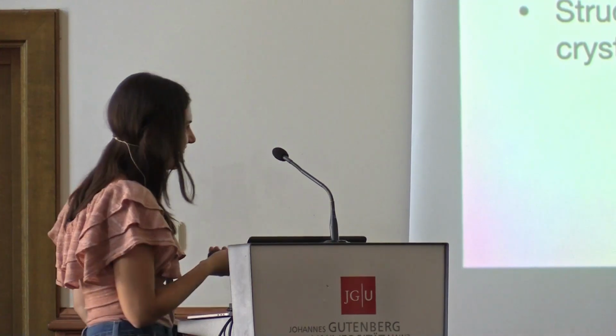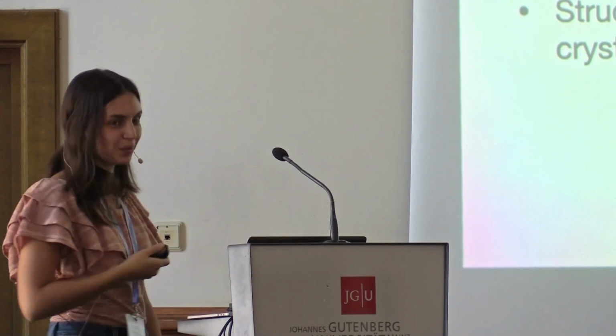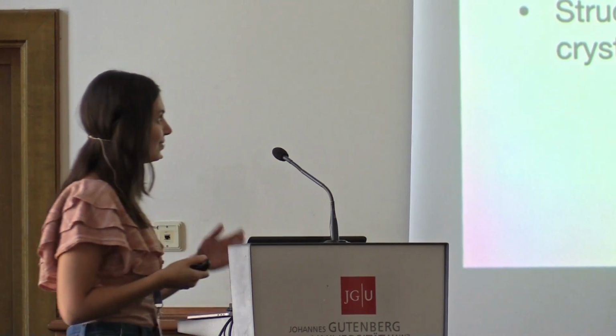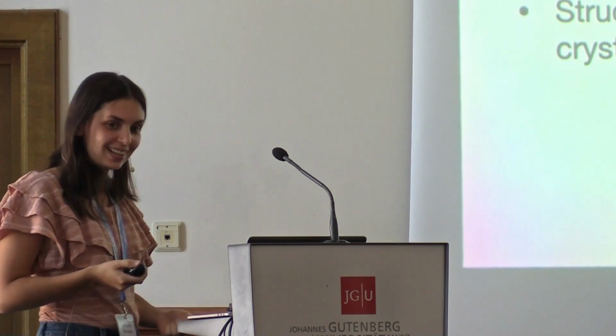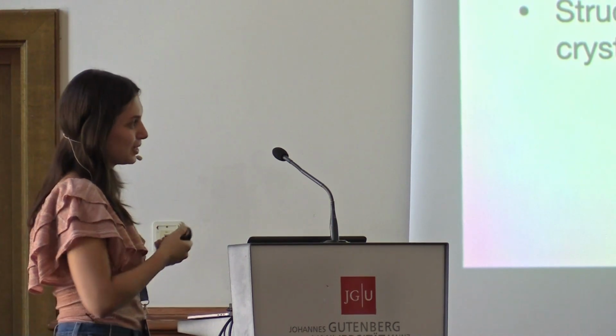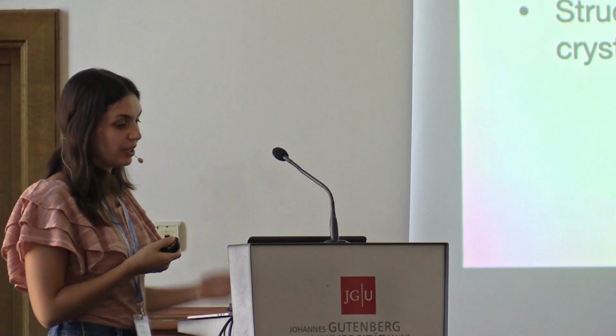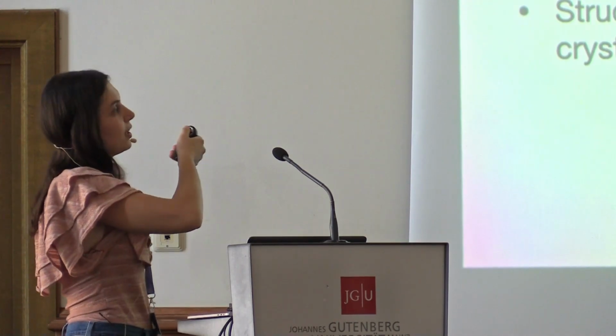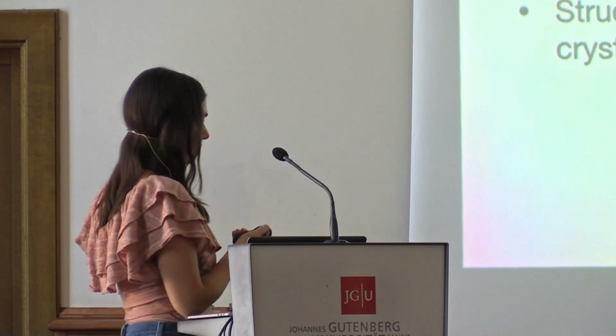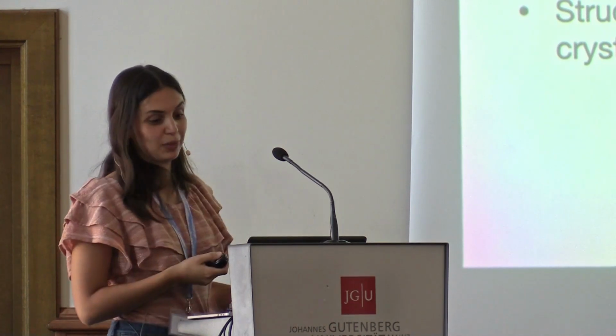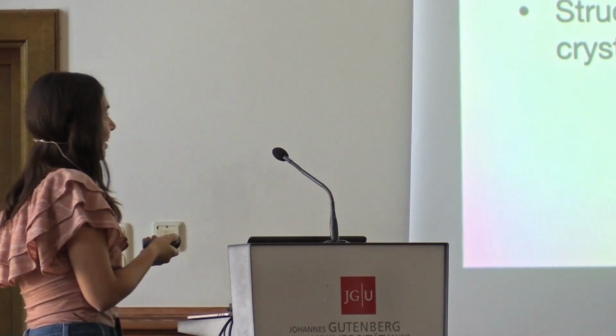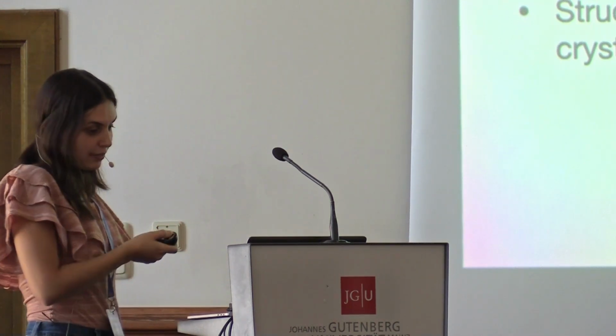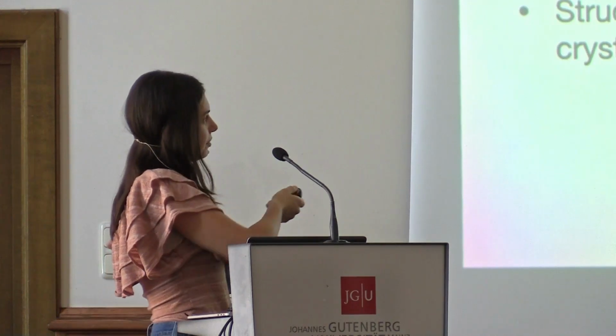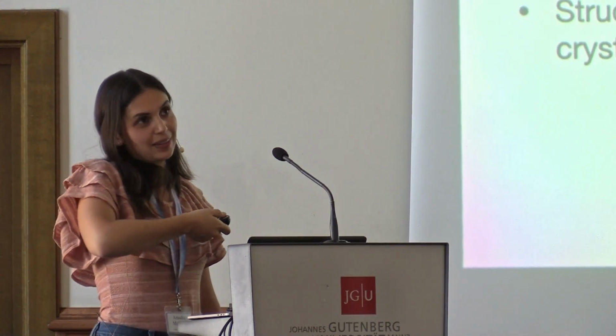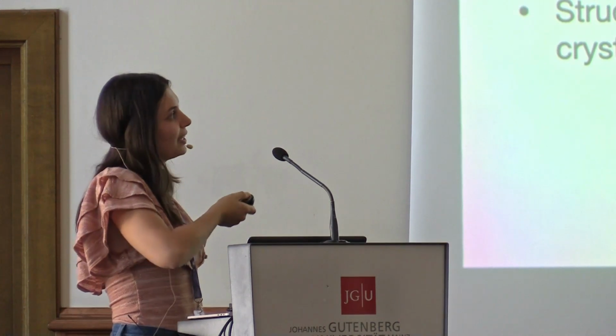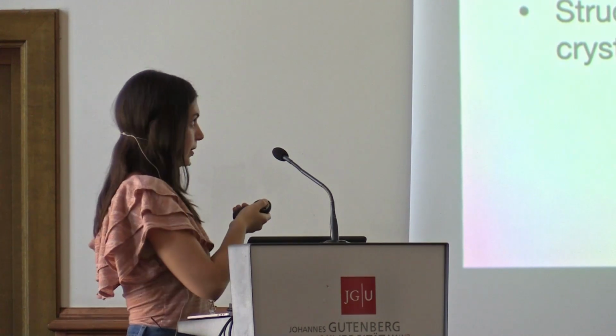I figured the first question people might ask is, what material do you have in mind for this setup? It's not totally clear yet, but we believe there's a number of reasonable candidates at the moment. When we're looking for a material, we're thinking about a high density of nuclei with large Schiff moments and low radioactivity. We don't want to heat up our experiment, and we don't want to hurt our experimentalists either. We want good acoustic properties, i.e. a high quality factor. We want strong piezoelectric properties because, as you saw from that material-dependent factor, it relates to having a large piezoaxionic tensor.